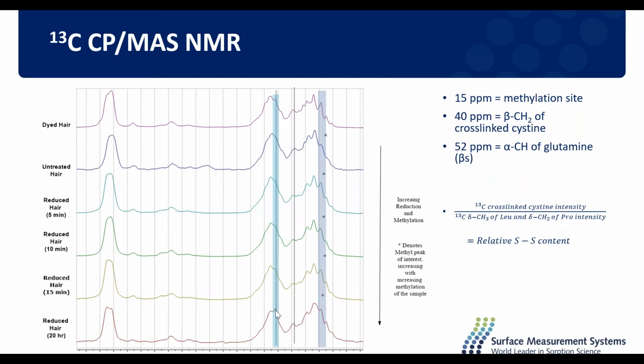And we know that this is likely due to those disulfide bonds breaking. And we can measure that directly. This last peak here at 40 ppm is the peak for the beta carbon of crosslinked cystine, or our disulfide bonds. And a reduction of this peak would indicate a reduction in disulfide bond content.